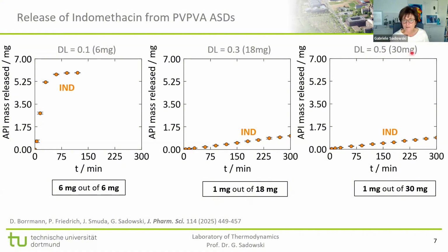So we now have 5 times the amount of the previous sample of 0.1. We have now 30 milligrams in a sample, and we still have only 1 milligram released. That means increasing the drug load does not solve the problem at all, but makes the problem even bigger. And don't forget that we are talking about very expensive compounds here. So we increase the amount of the therapeutic compound, and what we get is the problem getting bigger and bigger.